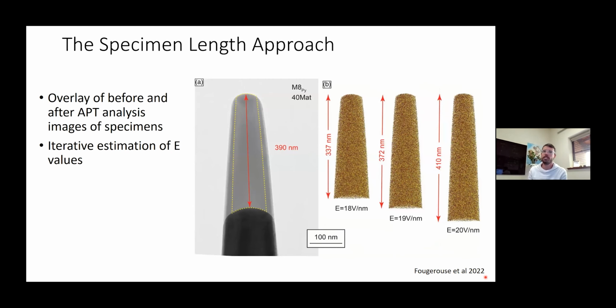So the approach we've taken with some success is to overlay images of atom probe specimens before and after analysis. So analyzing it for some time and then overlaying the two images to measure with as much accuracy as possible the length of the material we have removed during the analysis.